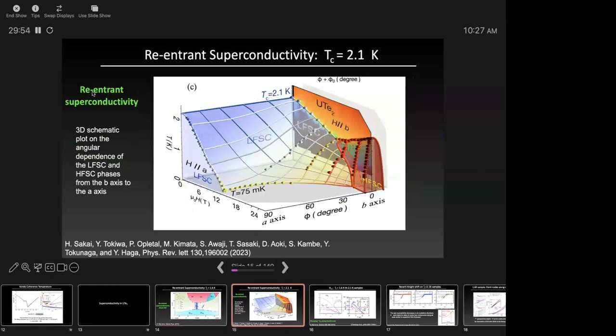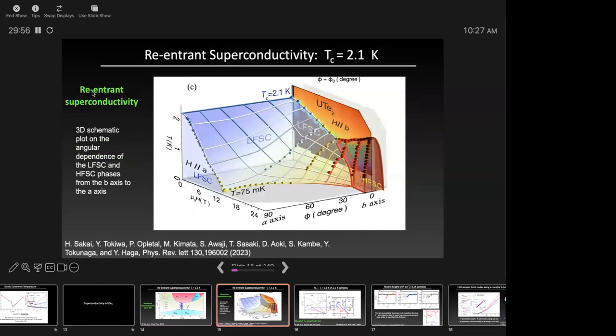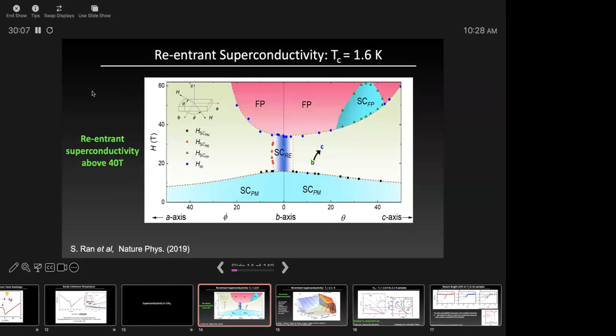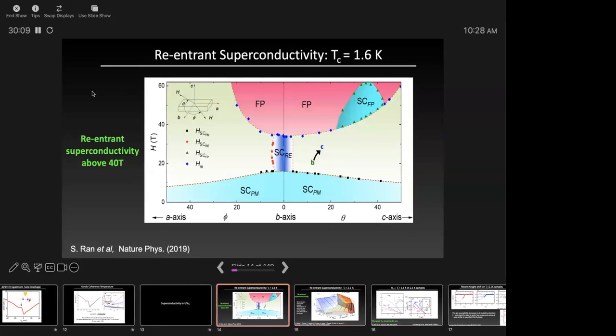Okay, just because yesterday there were so many questions on this other 2.1 Kelvin sample, I thought I'd show you some data on that sample. So let me just clarify. The initial samples had a TC of 1.6 Kelvin. And then later on, as the samples got cleaner, the TC has gone up to about 2.1 Kelvin.